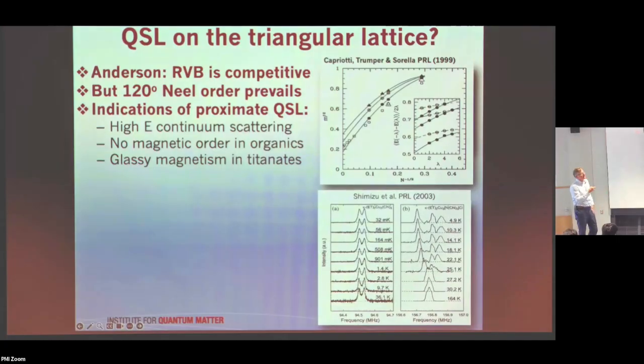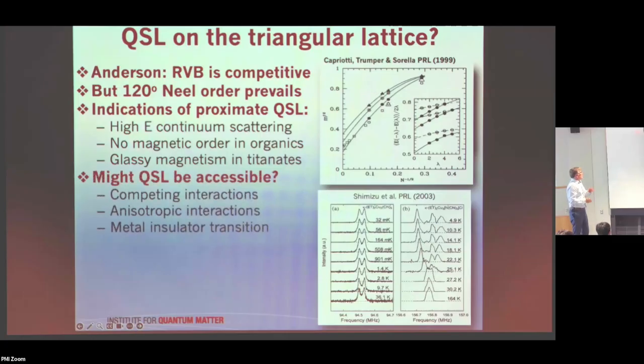There are some titanates that I think are very interesting, but are difficult to grow as single crystals, that show this absence of a phase transition to the 120-degree structure. And also these organic magnetic materials, in NMR they show really no indication of a phase transition at all. And so there have been persistent experimental indications that there is some kind of strongly fluctuating state lurking around out there that needs to be properly understood. Maybe it could be accessed with competing interactions or anisotropic interactions, or maybe if you have charge mobility, charge hopping, if you're near the metal-insulator transition.